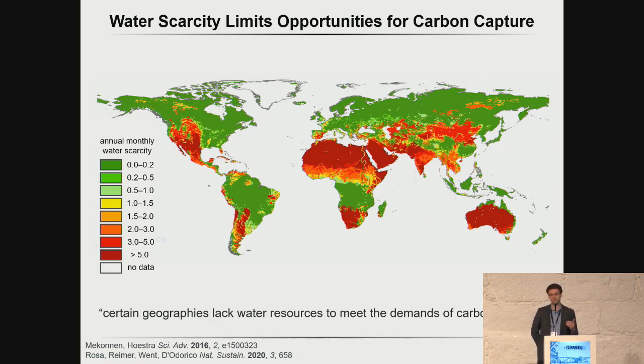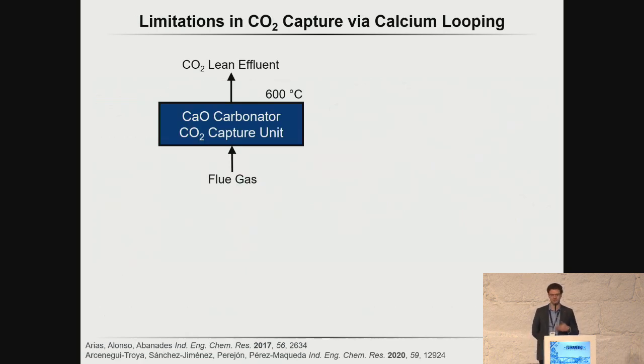So if we can't undergo carbon capture at modest temperatures associated with aqueous amines, we need to be thinking about capturing carbon dioxide at temperatures more associated with the emitted flue gas. And this is quite a developed field in terms of sorbents. The idea of using sorbents for high temperature CO2 capture is quite well developed using processes such as metal oxide looping. And what I have displayed here is a relatively high technology readiness level technology known as calcium looping.